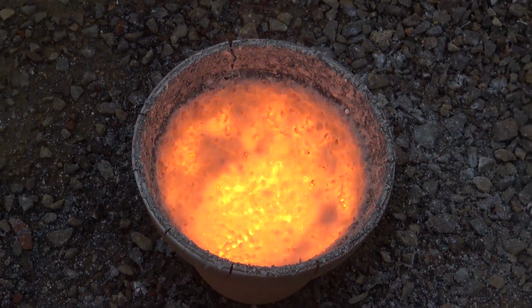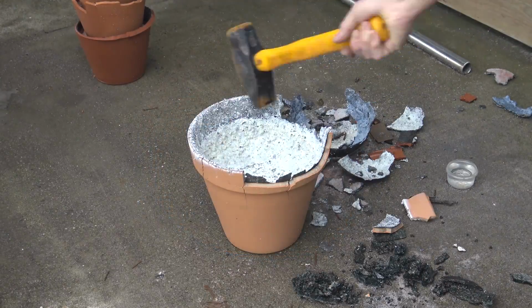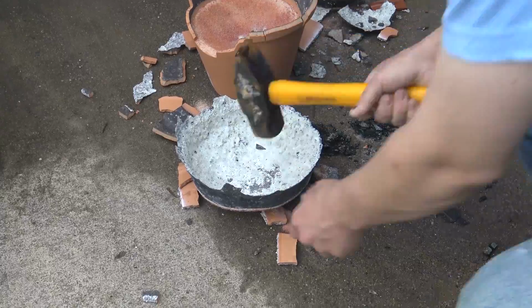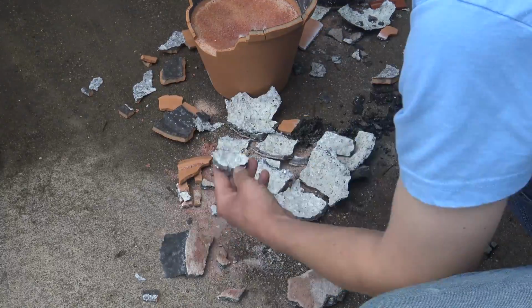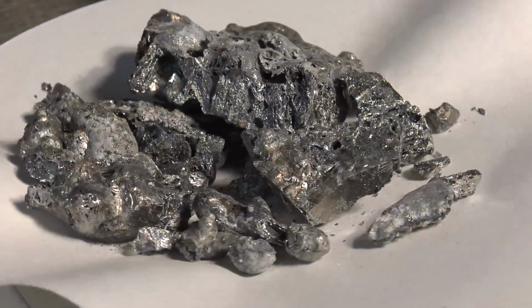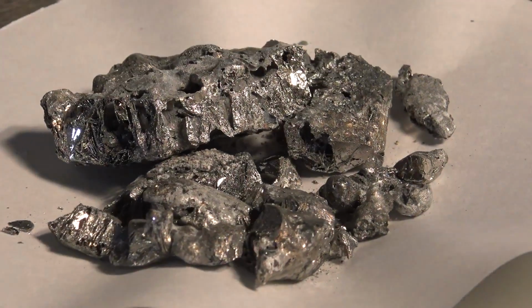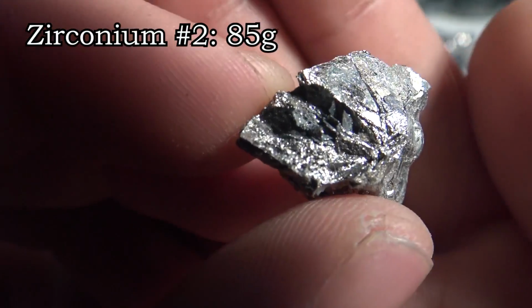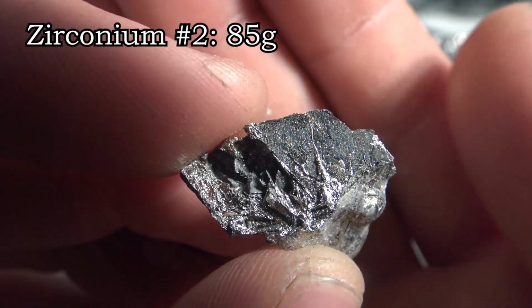Now that was impressive, and it looks like the addition of the extra flux to the mix helped hold at least some of it in the pot. Now let's see what we got inside. And it looks like we had more metal aggregate and crystal growth in the same fashion as the others, totaling 85 grams. Interesting for sure, but I'm still not sure why this is doing this.